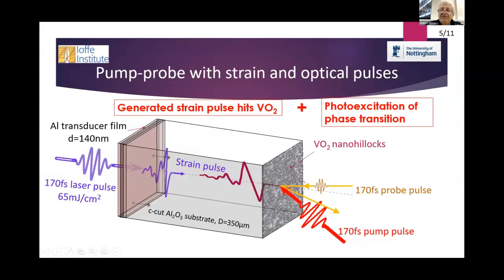So we have a vanadium film, which is not actually the film. There's a VO2 nanohillocks — we call them nanohillocks. Actually, these are vanadium dioxide nanoparticles, which are standing separately on the sapphire substrate, and then we generate quite high amplitude strain pulse, which is generated in aluminum transducer.